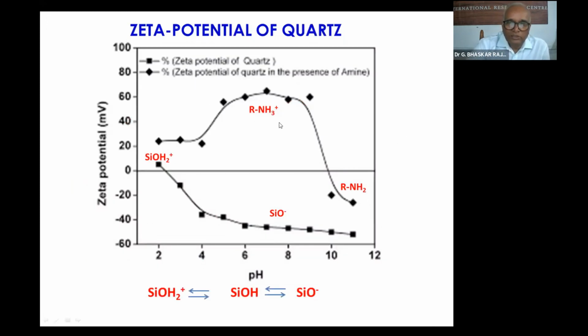Now let us look at silica as an example. When you put silica material into water, it forms a positively charged species, SiOH2+, at very low pH, around 2 or 2.5. This is the positively charged region. After this pH, it is negatively charged, that means SiO-. Exactly at this point, zero charge, it is in the form of SiOH. There is no charge. Below this pH, it is in the form of SiOH2+, and in alkaline conditions you have the SiO- form.